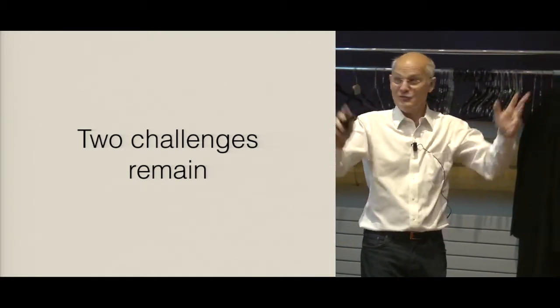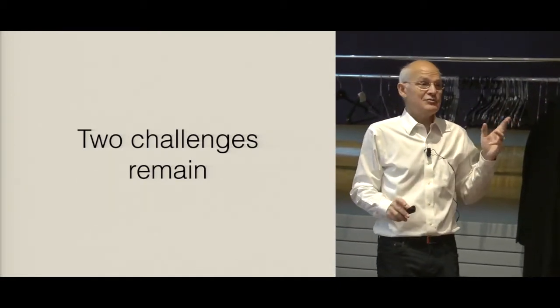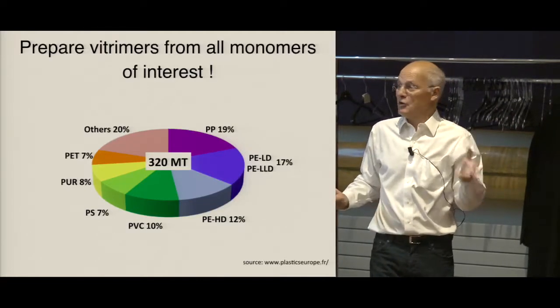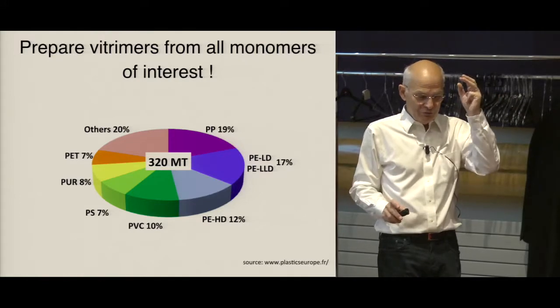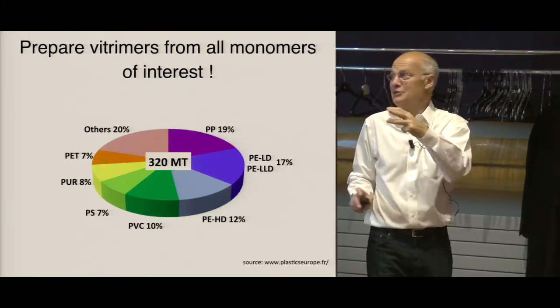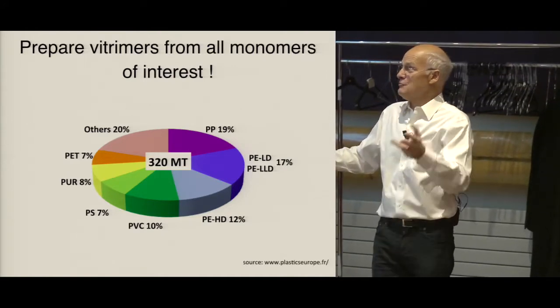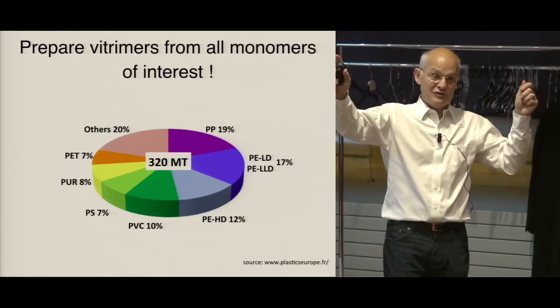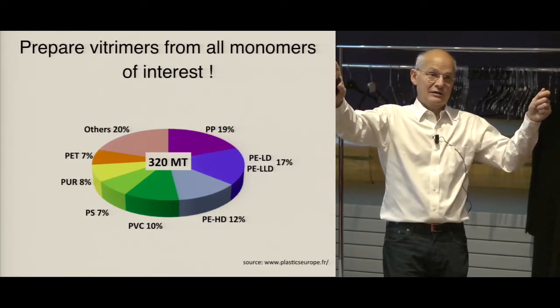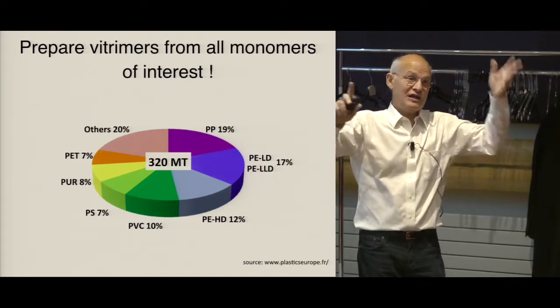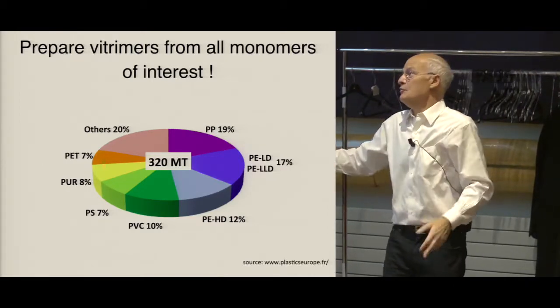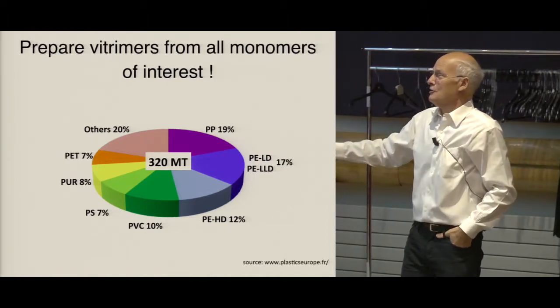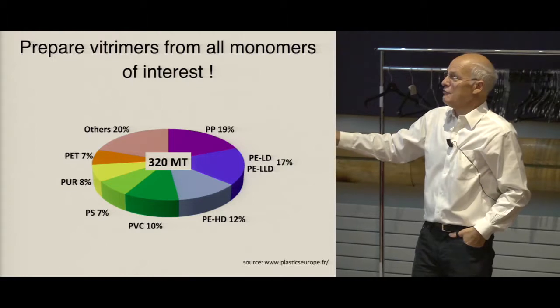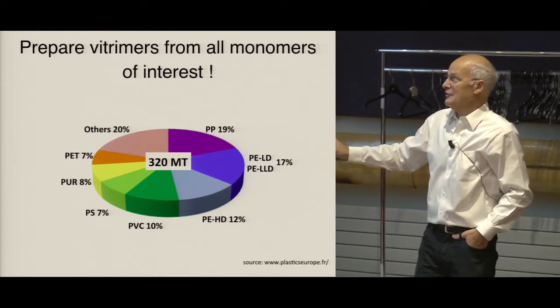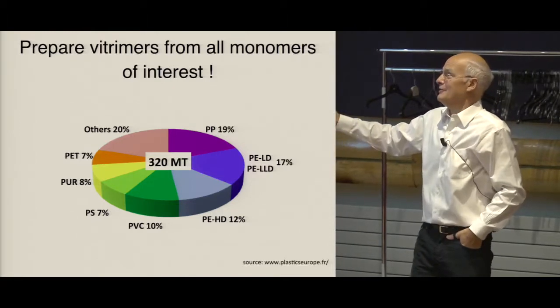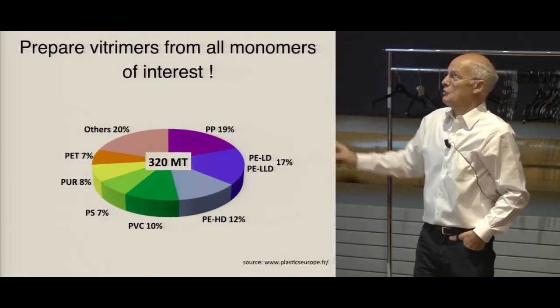And at this point, there are a lot of efforts and many papers which are done on vitrimers with chemistry. But none of these chemistries could make polymers from the monomers, from the materials that were mostly used as polymers. What I mean is that all these chemistries which were developed always had heteroatoms in the backbone. And you know that most organic compounds are carbon, carbon, carbon, carbon and hydrogen. So most of the polymers which are produced are polyolefins, polypropylene, polyethylene, maybe polystyrene. There are acrylics and others. And so this was the first challenge: how to make the polymers from the monomers of interest.